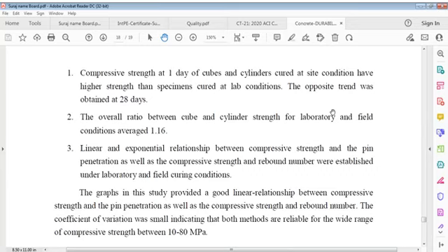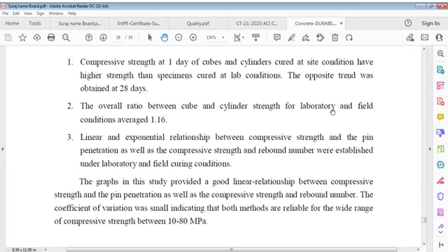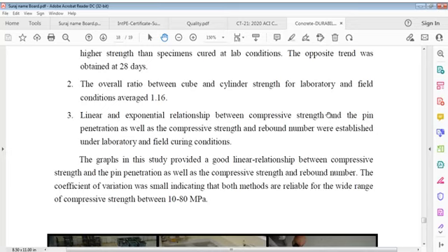Linear and exponential relationships between compressive strength and pin penetration, as well as compressive strength and rebound number, were established under laboratory and field curing conditions. The graphs provided a good linear relationship. The coefficient of variation being small indicates that both methods are reliable for the whole range of compressive strength between 10 and 80 MPa. That is the relation between compressive strength and pin penetration as well as rebound hammer.